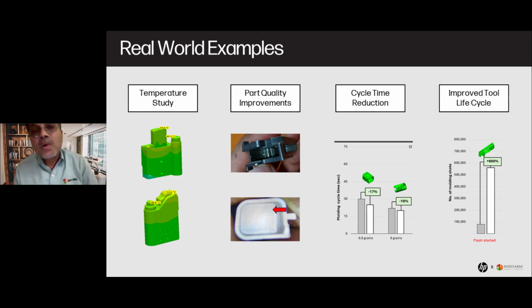Now, coming to the real-world examples, these are taken from our operation, our tool room. How do we know that binder jet 3D printing achieves the required success compared to the conventional method of manufacturing? So what we did was focus on a few key elements. As we all know, in an injection molding process, it's important to have a uniform temperature on various elements of the mold so that you can mold efficiently and cool the part efficiently. So we focused on a temperature study of the various sections of the tooling on the 3D printed mold elements to see if there is any advantage. Once we looked at that, we also compared what kind of quality improvements we were able to achieve on the component by using the binder jet 3D printed mold elements. And obviously, we were also looking for cooling time reductions.